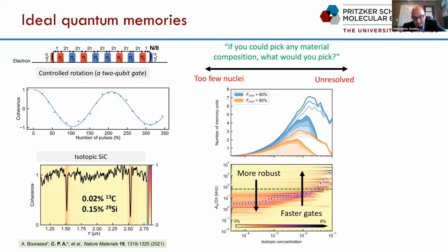So obviously, when you have something that's more weakly interacting, the trade-off is you're weakly interacting with it. It's only coupling very weakly, so the gate times become quite long. Here, I think the longest gate time we considered was 1 millisecond. We have some assumptions about what parameters we thought were reasonable versus not reasonable. For this system, at these temperatures, the T1 time is essentially seconds or longer.